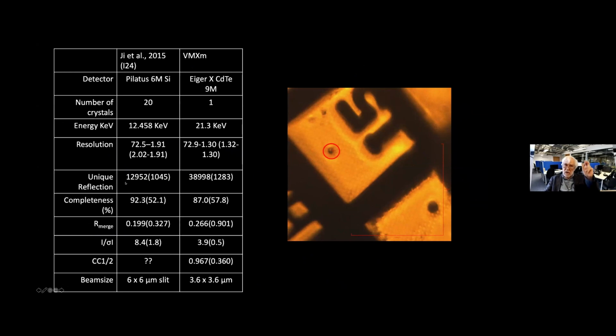And if we look at the data that you can get from this beamline, this is comparing it with the previous generation of microfocus beamline, which was called I-24. The published analysis of this structure required 20 crystals and achieved a resolution of 1.9 angstroms. Now, using a cadmium telluride detector, high energy, a single crystal can give a 1.3 angstrom resolution structure, orders of magnitude better.